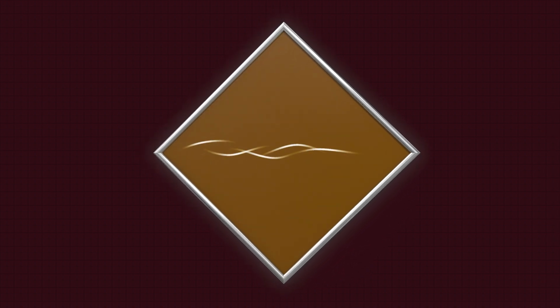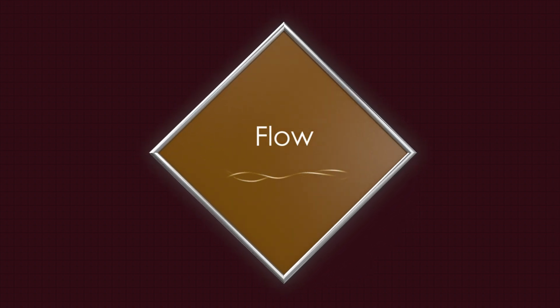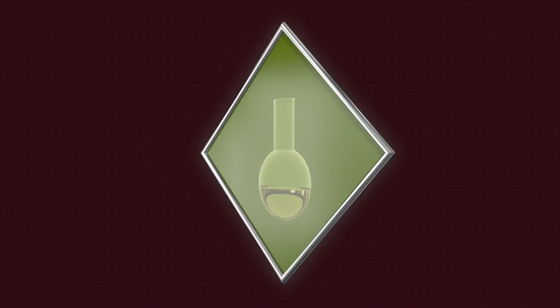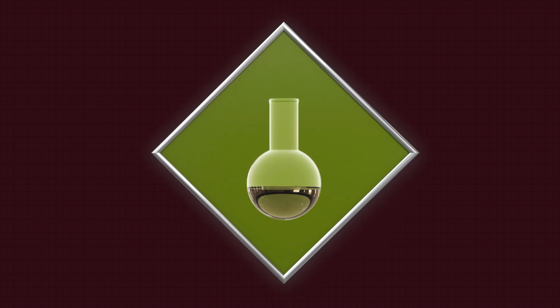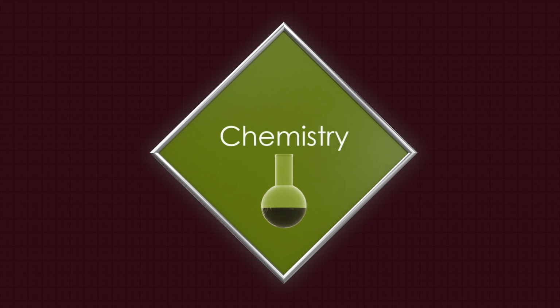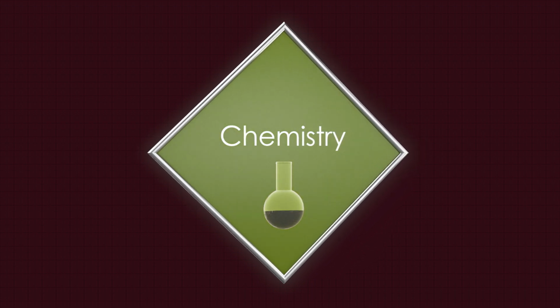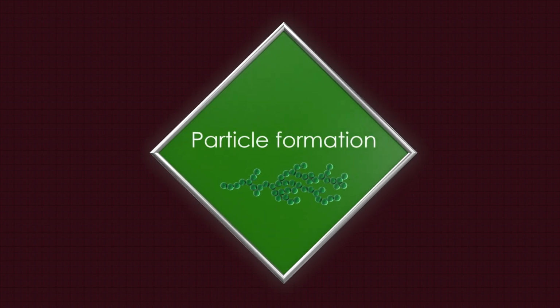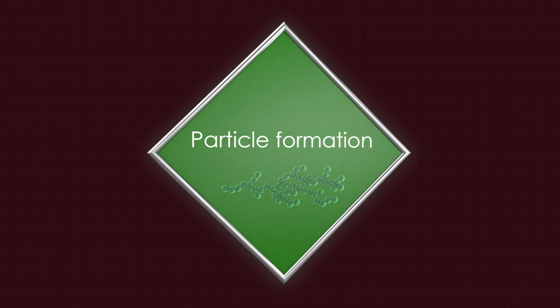What are the flow conditions, whether it is a turbulent flow or a laminar flow. They all determine, first of all, the chemistry of the reaction, how complete the reaction will be. But second of all, also the particle formation: how large the particles will form, how they will aggregate, and what will be their final shape.